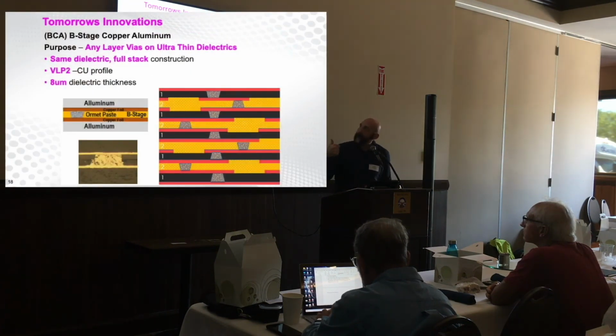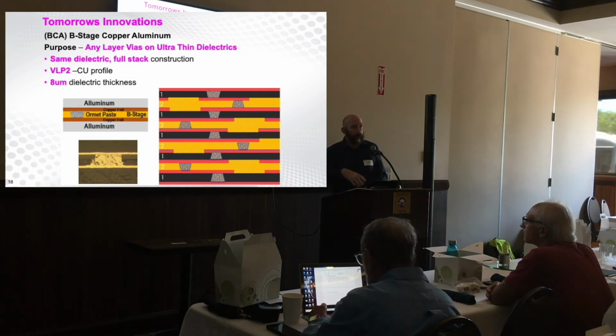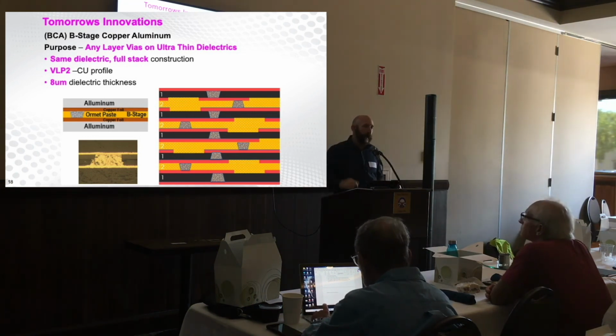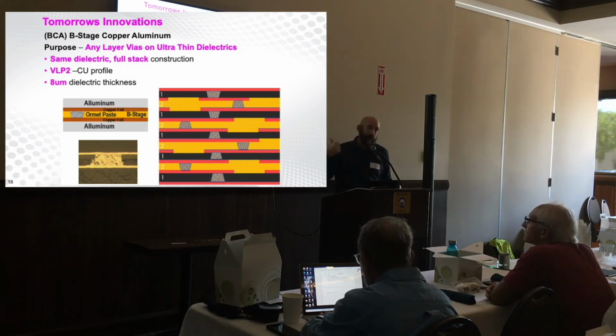So this is getting a little bit onto the R&D side. Imagine a fabricator has a sheet of material where you've got copper foil and B stage bonded to a temporary carrier. You laser drill, add the paste, you laminate foil on top of it. Now you've got a double-sided core with your interconnects inside, print and etch that, and now you can put those together. So there's a lot of different potential, a lot of different ways this can go.